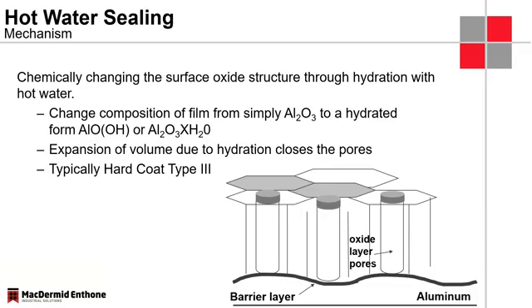If we look at the sealed surface here, this is the hot water sealing mechanism. What happens here is we created an aluminum oxide layer that does not have any crystal water. So through the immersion in hot water, hot deionized water, we will actually reintroduce crystal water to the oxide layer structure. And this reintroduction of the crystal water will actually swell the oxide layer. It increases in volume, and the only way it can go is inside the pores, and in that way it closes up the pores.